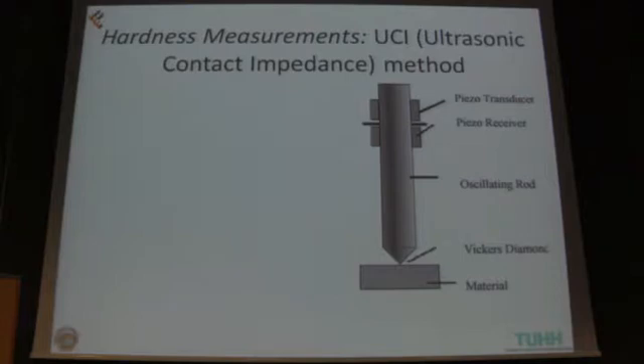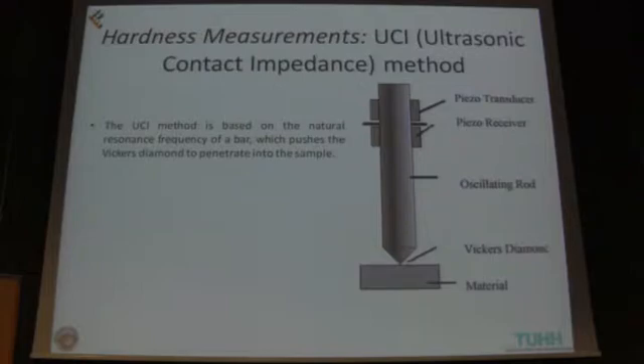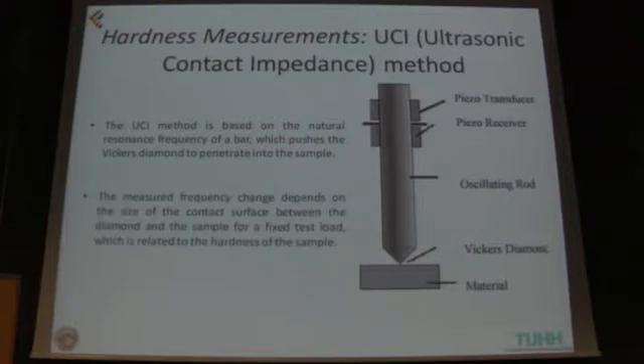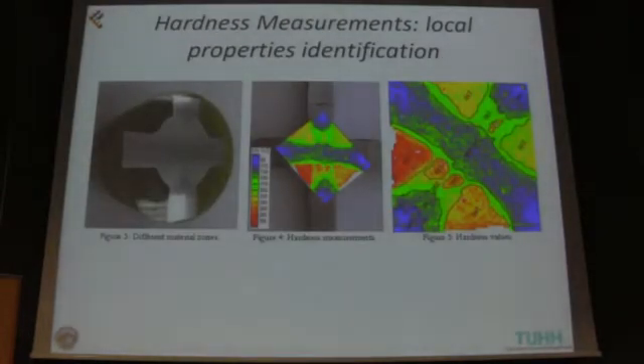The hardness measurements were performed with an innovative method, which is called the UCI method, which is based on the natural resonant frequency of a bar, which is excited, and pushes the Vickers diamond into the sample. This frequency changes, and these changes are related to the hardness values of the sample. The accuracy of the instrumentation is about 0.01 millimeter, and we are able to have a whole map of the hardness measurements.